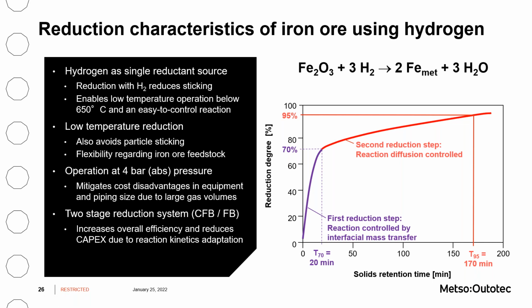The kinetics of the iron ore reduction are really fundamental to the Circored process. The overall reaction from hematite to metallic iron is shown up here. In reality, this is a sequential reaction network from hematite to magnetite to wüstite and then to metallic iron. Observing the reduction degree over time, one can distinguish 2 regimes, which are shown here on the graph. The first one, with fast reaction rates and a reduction degree of about 70% within 20 minutes, which is then shifting into a slower second reaction regime, which is controlled by intraparticle diffusion, indicated here in red on the graph.